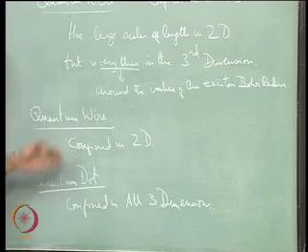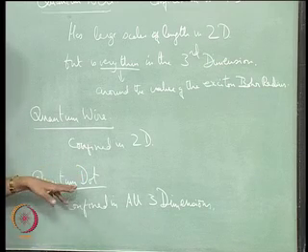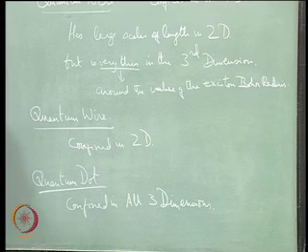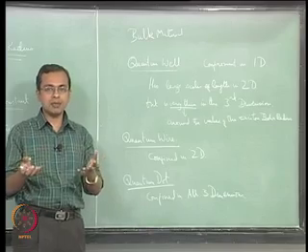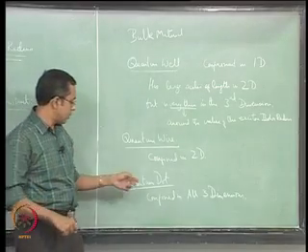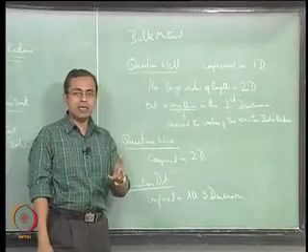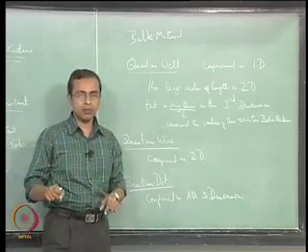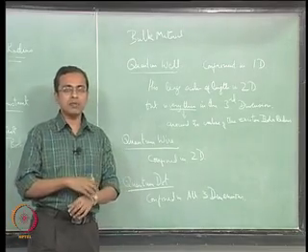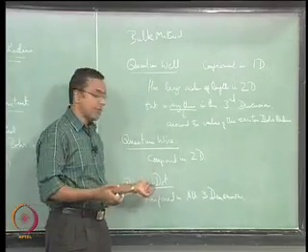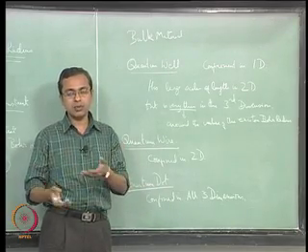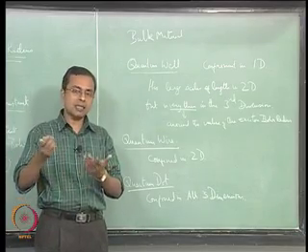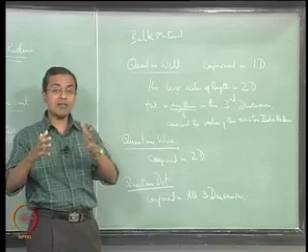There are of course a lot of very interesting scientific challenges in doing this, because when you make such tiny particles they are usually very highly reactive, so they will not stay as tiny particles for too long. They will simply react with each other and agglomerate, okay. So one of the scientific challenges is to freeze them such that they do not get in touch with each other and grow. One of the ways this is accomplished is to grow them inside a polymer matrix, okay. Many polymers have pores inside them which are in the nanoscale. So this would serve as a host matrix.